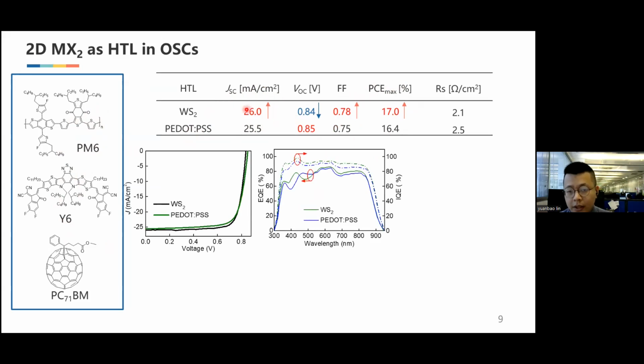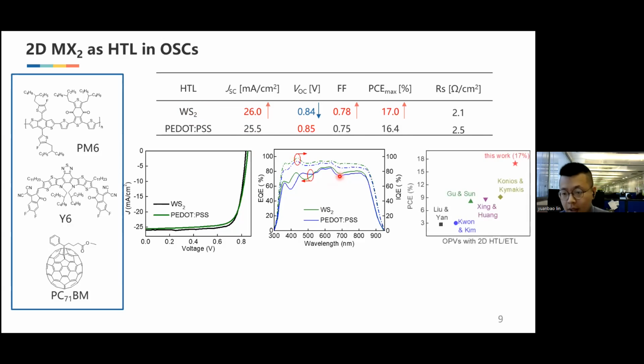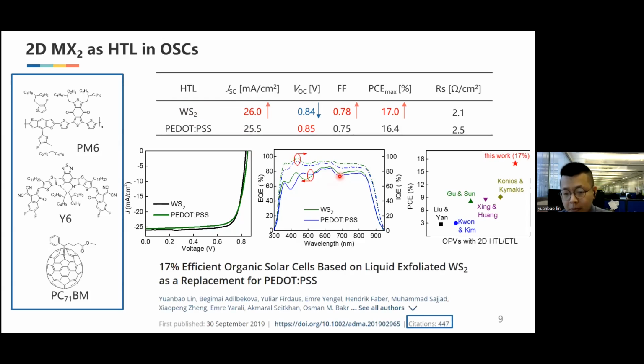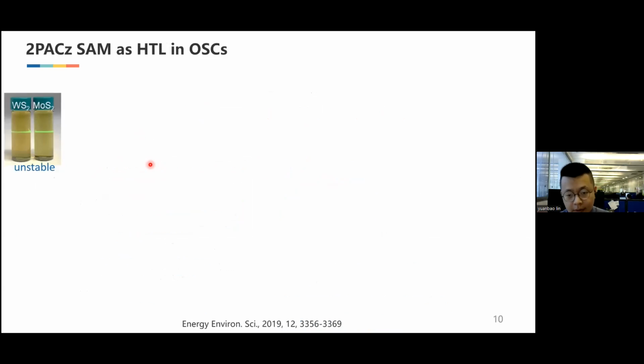The enhanced photocurrent is because of more photo response in this wavelength. This is because the PEDOT:PSS absorbs some light in the visible light and the near-infrared region. So when we use the 2D material, we can increase the photo response in this wavelength. And this work was published in 2019 and was highlighted by the Nature Energy journal.